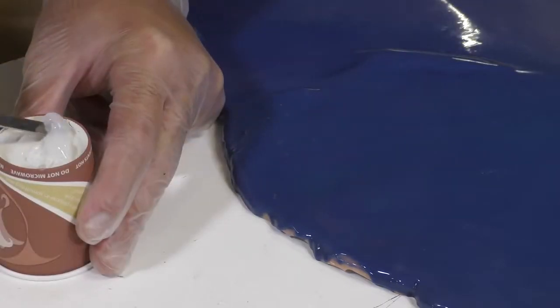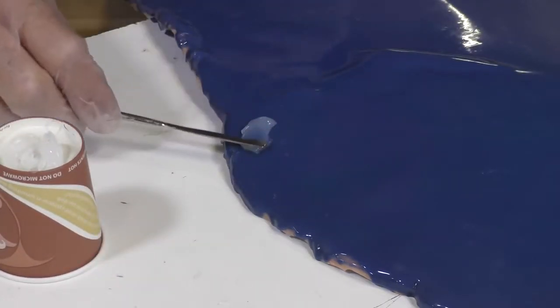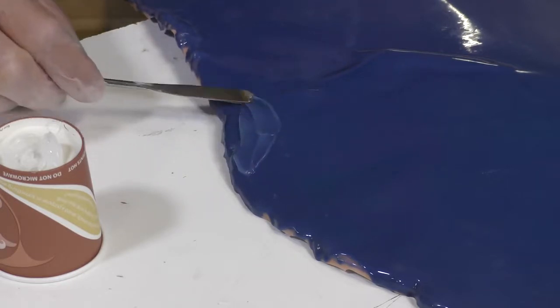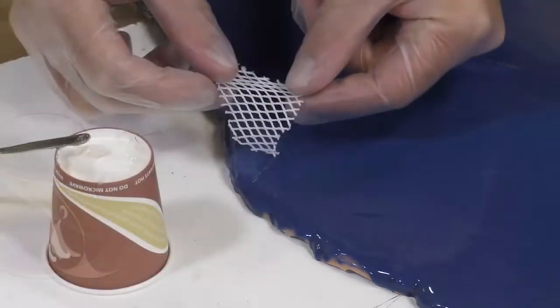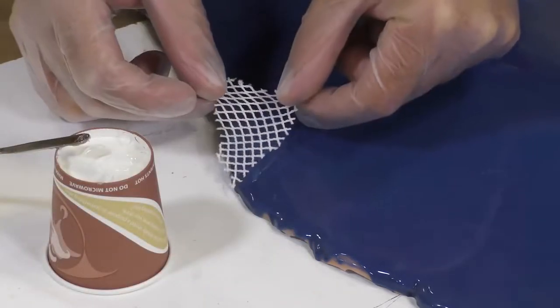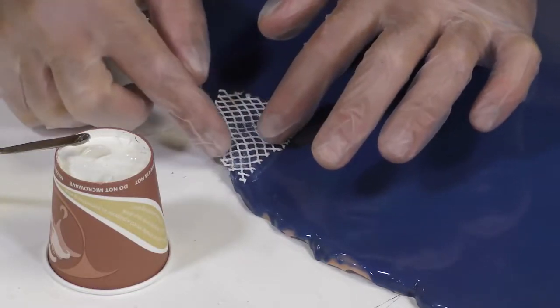Using the wide end on my sculpting tool I am applying a thin layer of Silpoxy one inch in all directions to ensure there is a base to set the reinforcement cloth into. This will ensure a good encapsulation of the reinforcement cloth all around the edges.